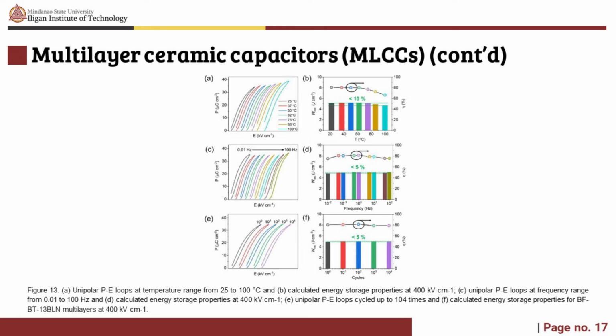The recoverable density value of the multilayers exhibits negligible degradation after 10,000 cycles of the unipolar PE loops, possibly due to the absence of significant strain at 400 kV per centimeter. The low strain prevents large cyclic changes in dimensions and eventual micro-cracking. Temperature stability is still limited mainly by the conductivity mechanisms, which become active under high electric fields. Nonetheless, in comparison to the polymer-based capacitors with similar energy densities, the materials show promise for high temperature applications.